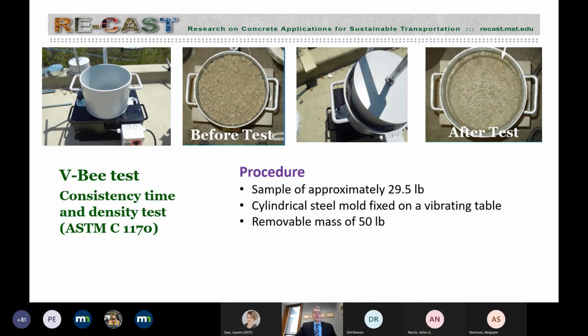In parallel to the placement, our research team from Missouri S&T was there doing a lot of testing, including the VB test. And you can see the VB test over here in the procedure. So you consolidate it over a vibrating table with an overhead load of 50 pounds. And then normally we stop the consolidation or the vibration once there's a halo of mortar seeping up, so there's a plate on top, and we say, okay, this is the time of ultimate consolidation. Unfortunately, that was not achieved.